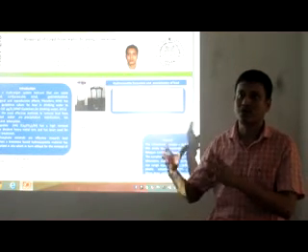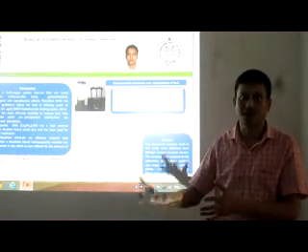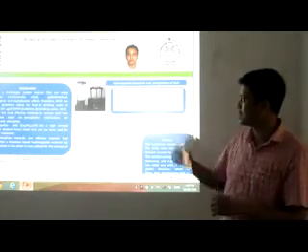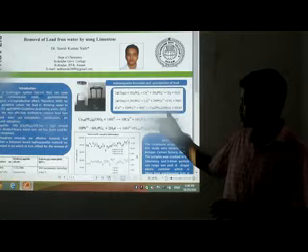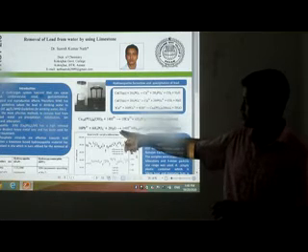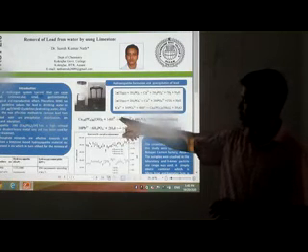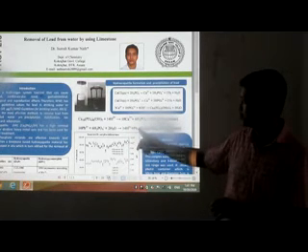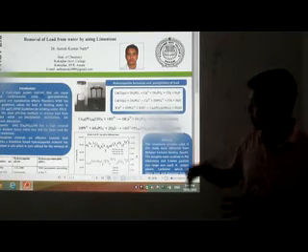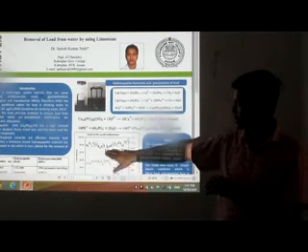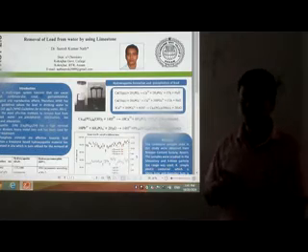What happens when phosphoric acid reacts with the limestone, it will produce hydroxyapatite within that chamber, and that hydroxyapatite will precipitate lead following this reaction. This reaction shows the formation of hydroxyapatite first, and then the hydroxyapatite will degrade in presence of the acid, and it will produce hydroxypyromorphite, which is having lead as a constituent. All this reaction has been established earlier, but this work we have tried in our laboratory, and we have found that more than 80% removal is there in this experiment.